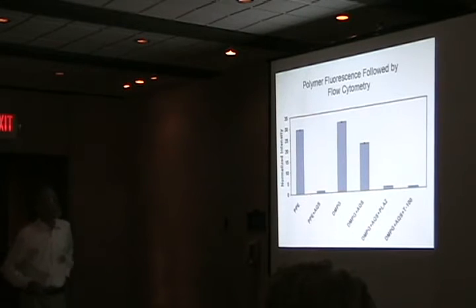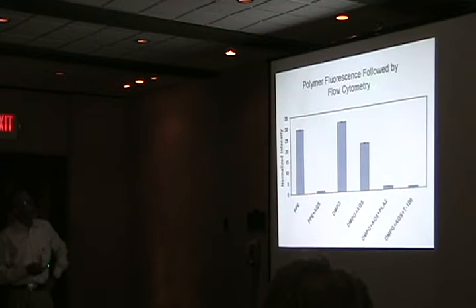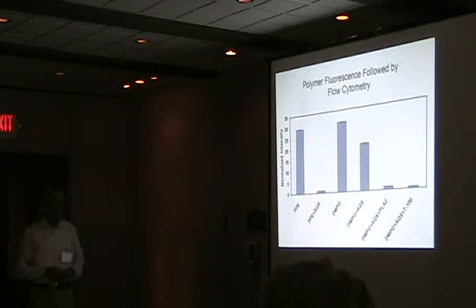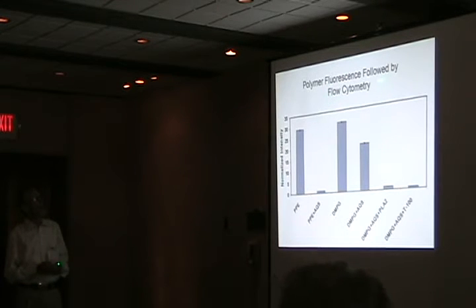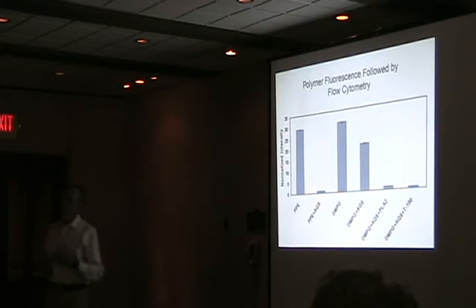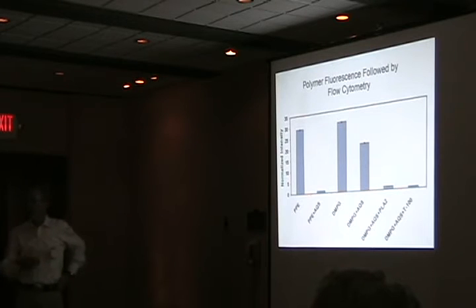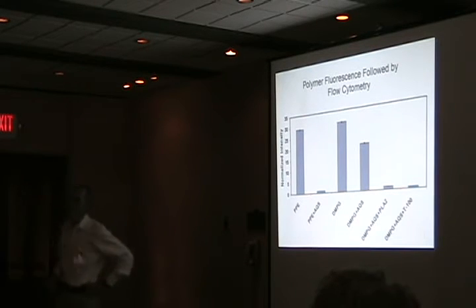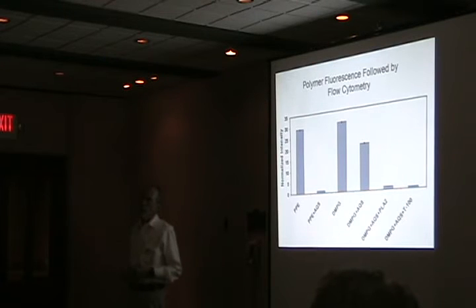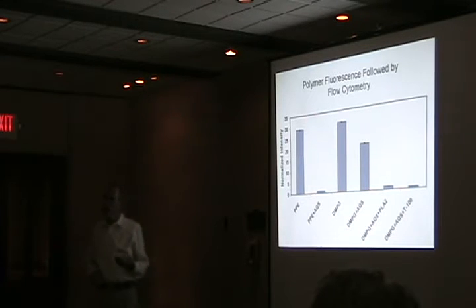We've actually been doing this by flow cytometry and also by conventional fluorescence. The flow cytometry is nice for this. It's very easy to do. And the interesting thing, the only way this will work in the flow cytometry, if you see quenching, is that the quencher is associated with the particle surface and is not swept away readily by the flow process.